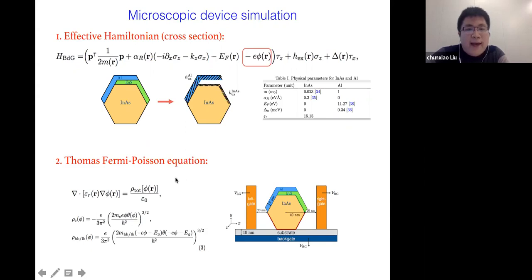In solving this self-consistent equation, we can include the effect of all the gates, the left gates, the right gates, and the back gate in the problem. Also important is the boundary condition between indium arsenide and the other material. When two materials are in contact with each other, the band offset, whether it's positive or negative at the interface, will determine whether electrons will tend to accumulate or be depleted from that facet. So a precise value of this band offset is important for getting a faithful electrostatic potential profile in this particular problem.